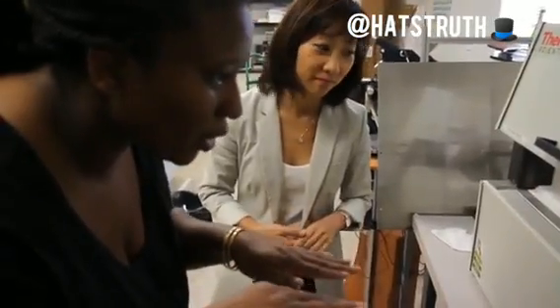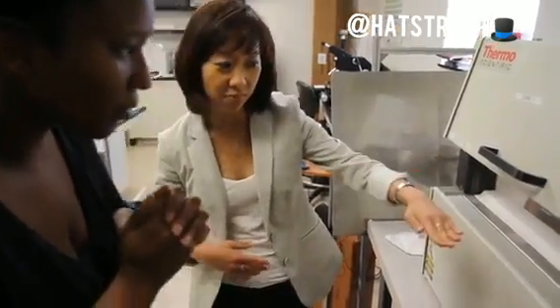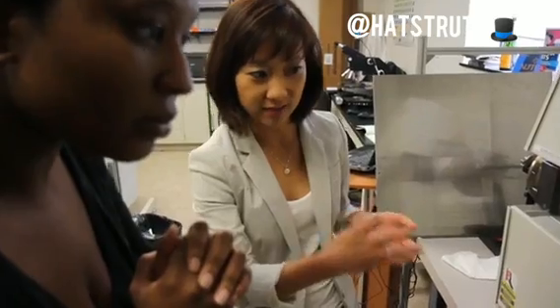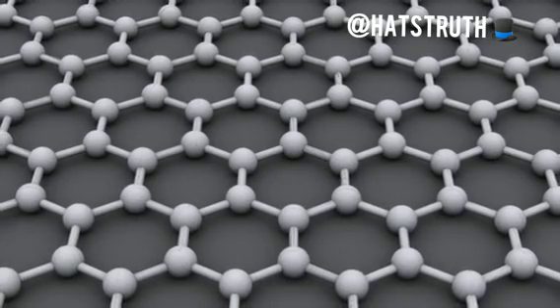Wow. And we flow different gases through the furnace, which then get deposited. The carbon gets deposited onto the copper, and you get a single layer formation of graphene, which is a hexagonal carbon lattice. So the copper is the base upon which you would put the graphene. Exactly. So actually, we put the copper in there. It has nothing on it. Okay. And we flow different gases, argon, hydrogen, and methane, where the carbon is derived from. And a single layer of graphene is deposited on that copper. Okay. So what you get is gas flowing through the furnace, heats up to 1,000 degrees Celsius, and deposits onto the copper in a single layer. And the crystal structure, the atom structure, really looks like a chicken wire fence. Okay. So it's a six-sided hexagonal structure.